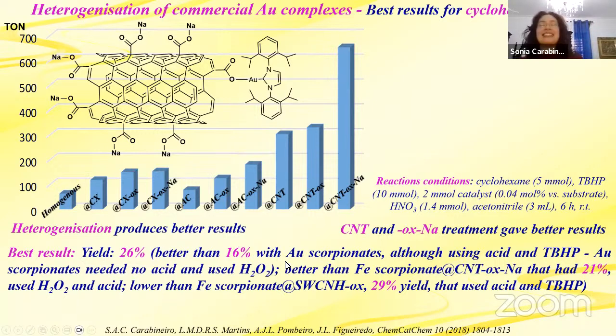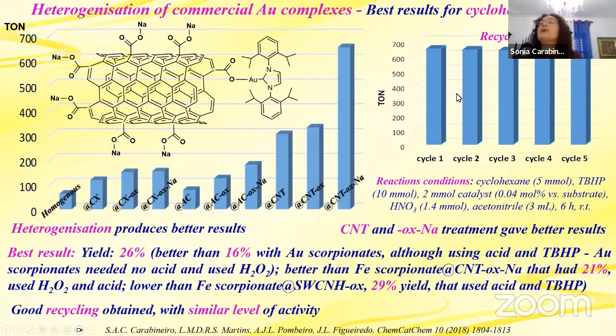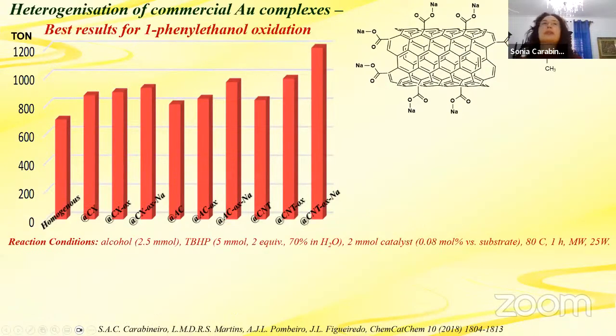But here we had to use acids, and the scorpionates did not need acid. And also the scorpionates used milder oxidants, that was hydrogen peroxide, and we had to use TBHP, the tert-butyl hydroperoxide. Also bad, but it was better than the iron scorpionates that had 21% and also used acid, but lower than the scorpionates on carbon nanohorns. Remember, had a 29% yield, but also used acid and TBHP. So we have to decide what we prefer. But okay, good recyclability was also obtained with similar level of activity, so not much deactivation. And again, high selectivity, no trace of byproducts.